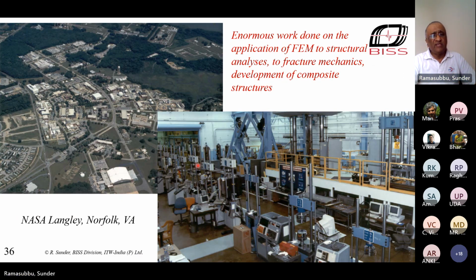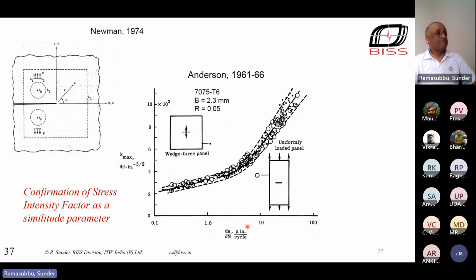Enormous work was done at NASA Langley in the US. Here's an aerial view of that area in the lab as it looked some years ago. The NASA Langley scientists, and amongst them were quite a few from India as well, many of them from the Indian Institute of Science, did a lot of work whose results are being used as references today in aircraft design. They came up with studies to confirm that the stress intensity factor is a similitude parameter. You can see here test results from a rivet loaded geometry where the stress intensity will come down with crack size. As crack size increases, K will come down. In a center crack, it will keep going up. But if you plot crack growth rate versus K, all the data fall into a single scatter band. It's a huge advantage, which I'll come to once again.